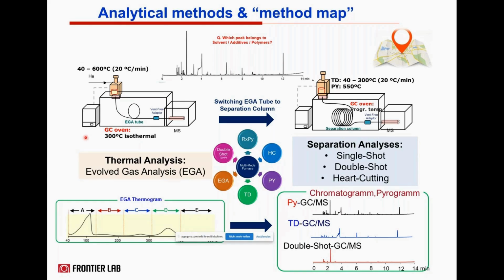Here, the sample is continuously heated in the pyrolyzer oven at a certain rate, for example, 40 to 600 degrees Celsius, while the GC oven is at constant temperature, e.g. 300 degrees Celsius. In this method, a short deactivated capillary, so no separation phase, is installed in the oven, so there is no chromatography and no separation. And with the MS detector, you get signals corresponding to the respective boiling points of the compounds contained. So at lower temperatures, the volatiles will be detected, and then at higher oven temperatures, high boiling materials are detected. And this thermal profile allows statements about the composition of the material, the complexity, and also the optimum pyrolysis temperature.